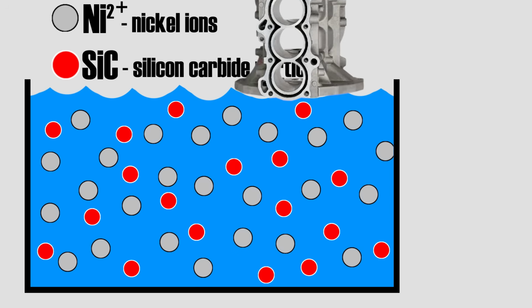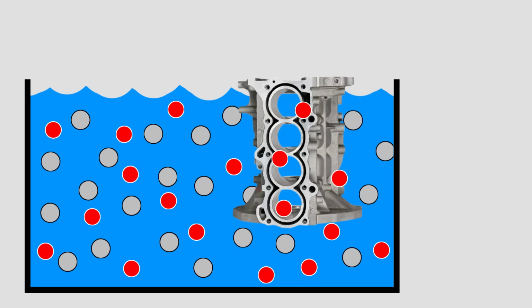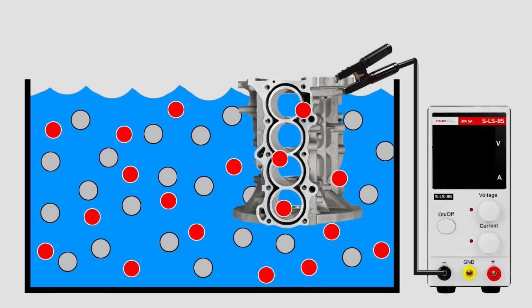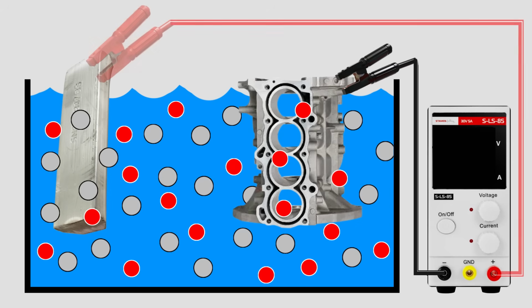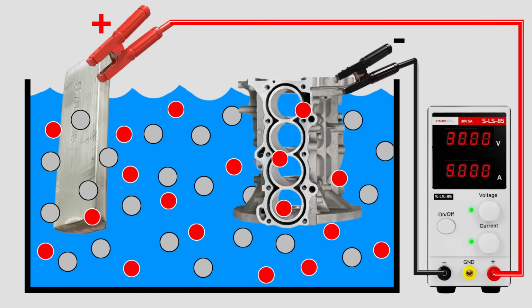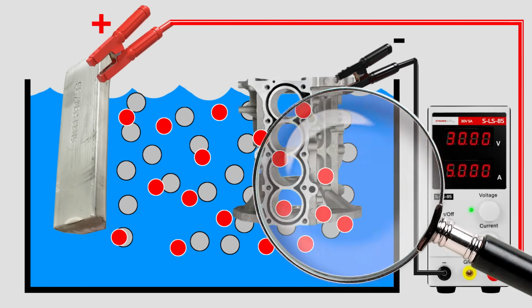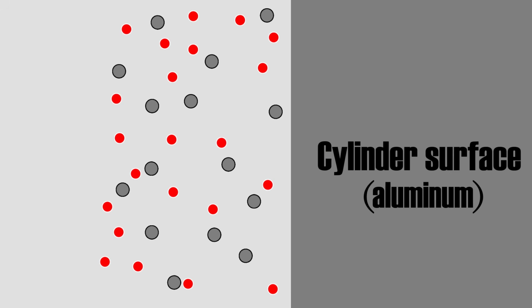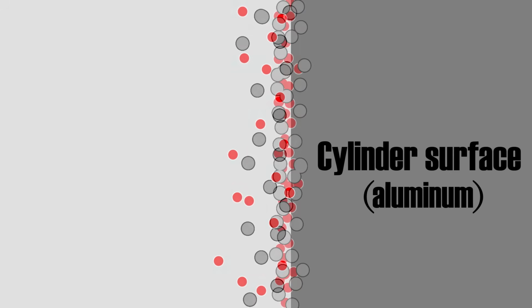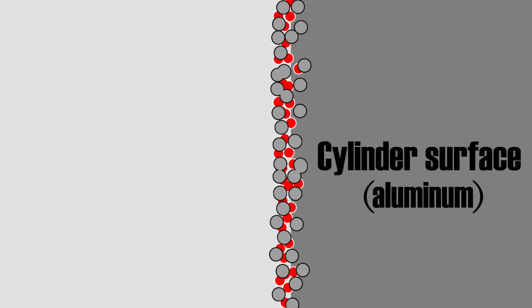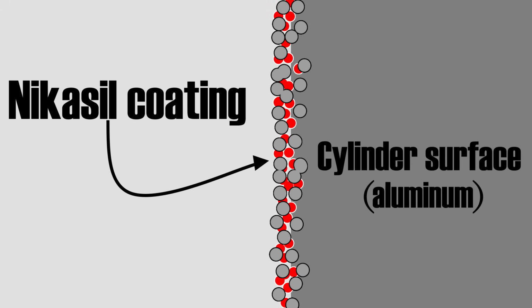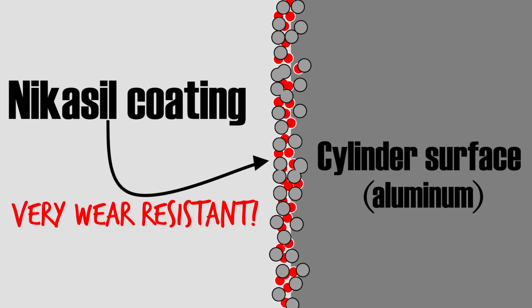What we do is that we put our cylinder block in the bath, and then we connect the negative side of a power source to that block, which makes the block our cathode. And then we take a nickel bar, dip it in the solution, and connect the positive side of our power source to the nickel bar, which makes it our anode. When we turn on our power source, electricity of course starts flowing from the anode to the cathode. Nickel ions from the solution move toward the cylinder and coat its surface, whereas silicon carbide particles get trapped in the nickel layer, creating a very thin, but at the same time very hard and very wear-resistant Nikasil coating.